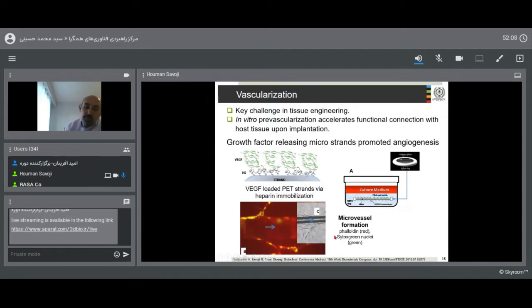So we have the microvessel formation. The only challenge is that you can have angiogenesis or vascularization in thin tissue because endothelial cells do their job. The endothelial cells tend to make these microvessels, or promote angiogenesis, in contact with growth factors, for example VEGF, EGF, or other growth factors. But this is really for thin tissues. These blood vessels or microvessels here are not perfusable. They are not open. They don't have open lumens. So that's a real problem for thick tissues.